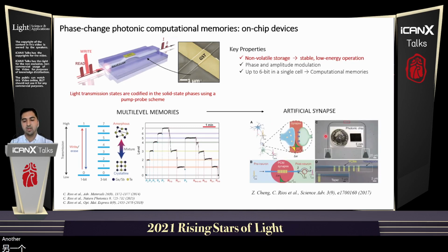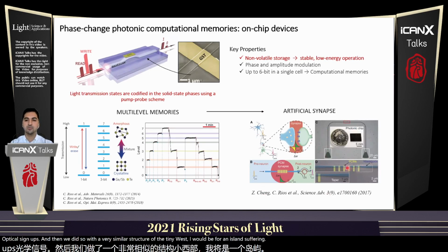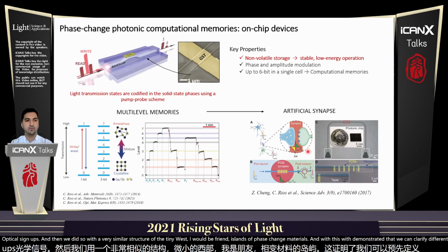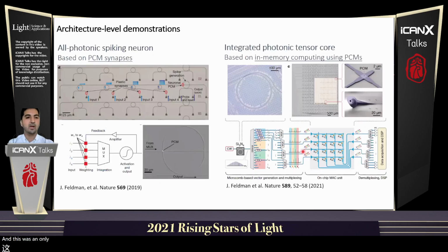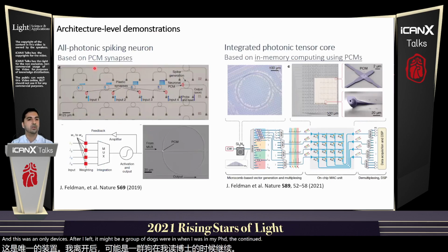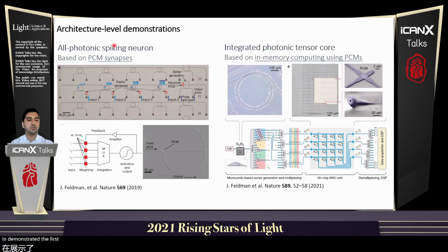Another application we did is we demonstrated the first on-chip optical synapse. And we did so with a very similar structure, a photonic waveguide with different islands of phase change materials. And with this, we demonstrated that we can codify different weights of information in the transmission of light. And this wasn't only devices. After I left my group at Oxford, where I was doing my PhD, they continued to work and took the phase change synapse and demonstrated the first all-photonic spiking neuron.